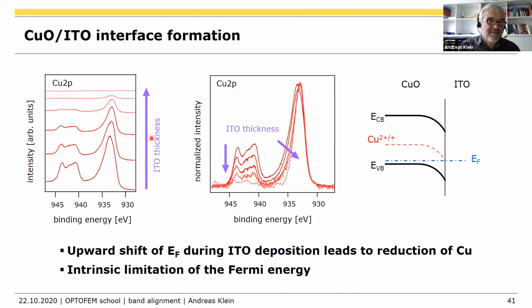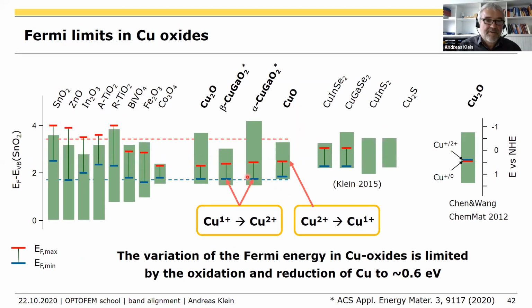And we can show that by depositing ITO. You see this satellite peak. This is a characteristic feature of the copper 2+ oxidation state. And if you deposit ITO, the Fermi level goes up, we bend the bands down, the copper 2+ disappears. Okay, the similar thing happens for Cu2O and for copper gallium oxide.